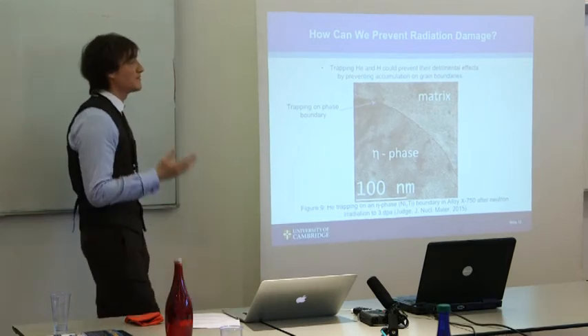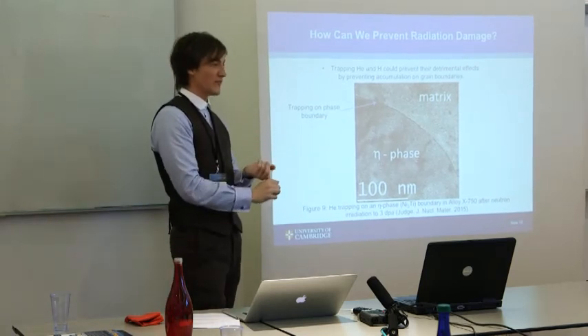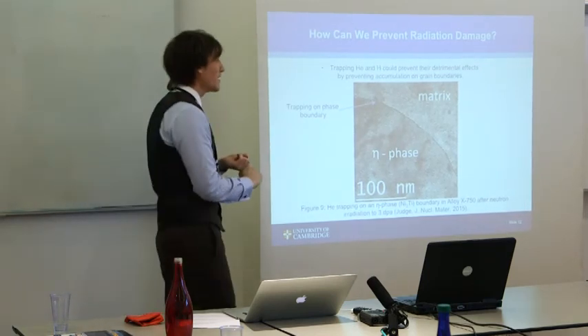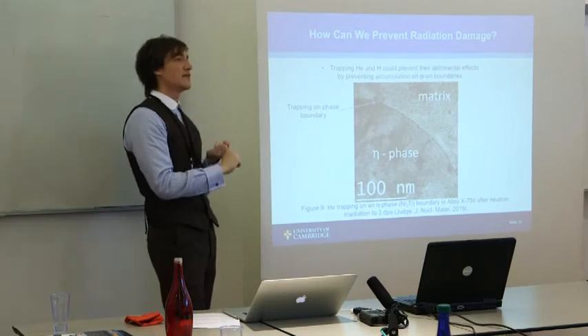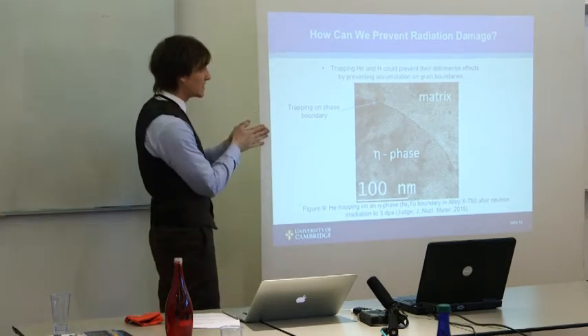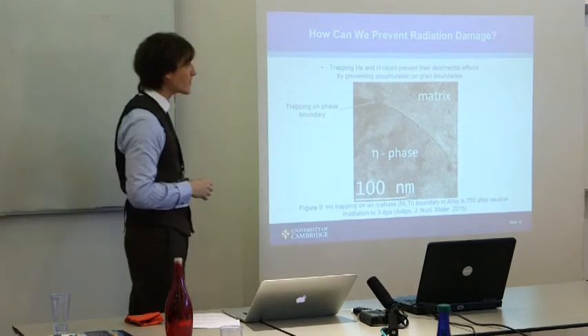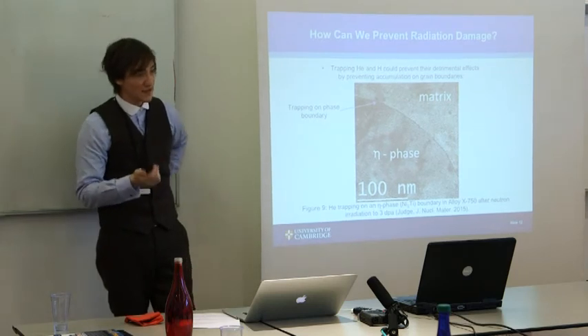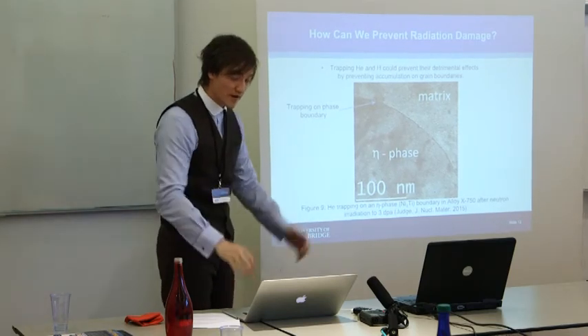How can we stop it? If helium is produced by nickel in the grains and boron on the grain boundaries, you can eliminate boron on the grain boundaries and solve part of the problem — but you've still got helium production from nickel in the grains diffusing to grain boundaries. One solution is to trap it before it gets there. Eta phase has been shown to trap helium not only on grain boundaries but at the interface of the eta phase with the matrix. If we can optimise materials to produce such interfaces and secondary phases, we could prevent helium conglomeration on grain boundaries and stop grain boundary embrittlement.